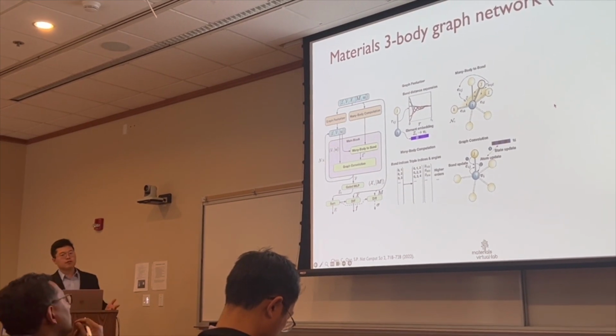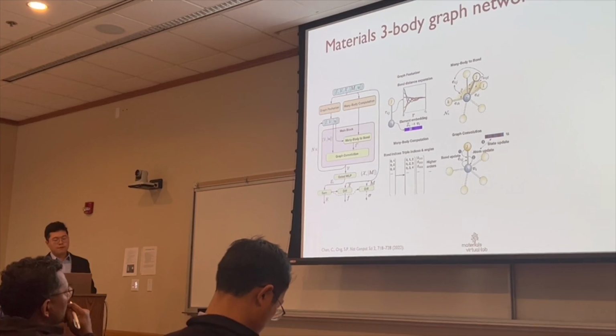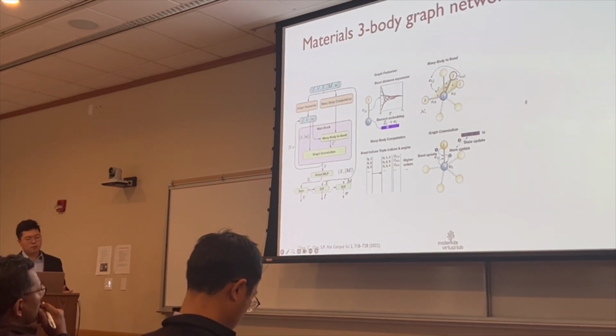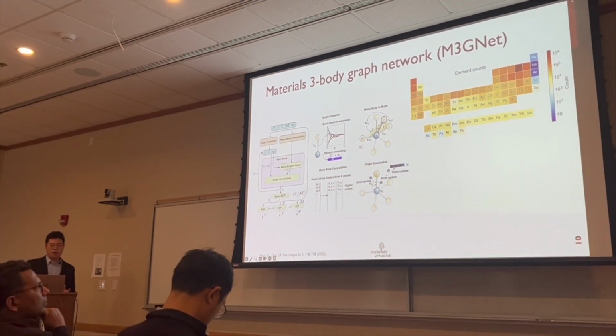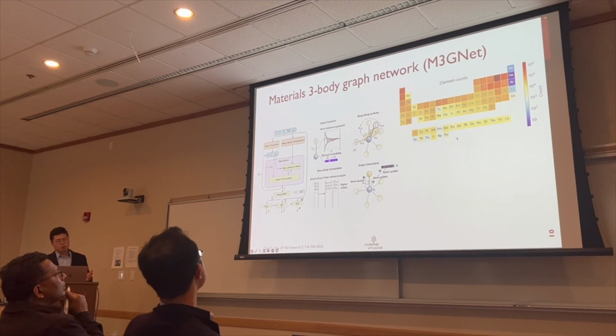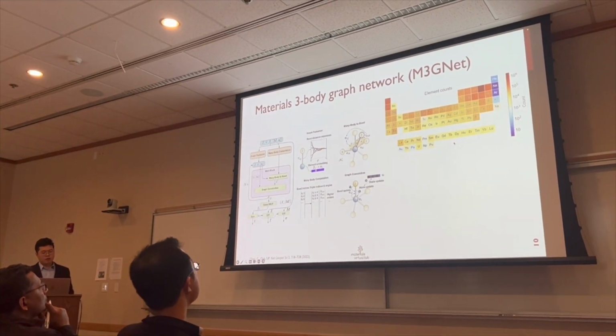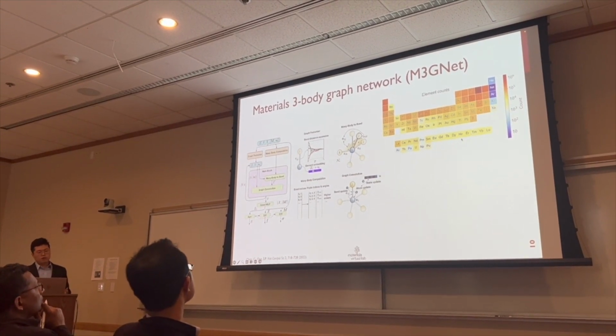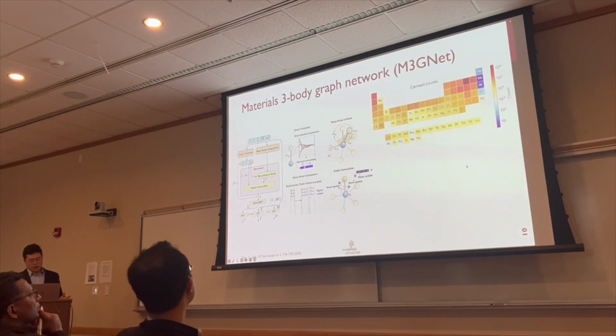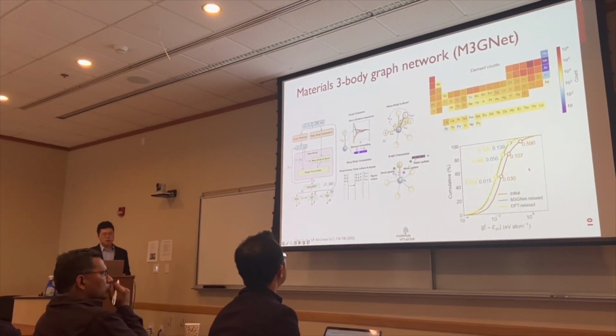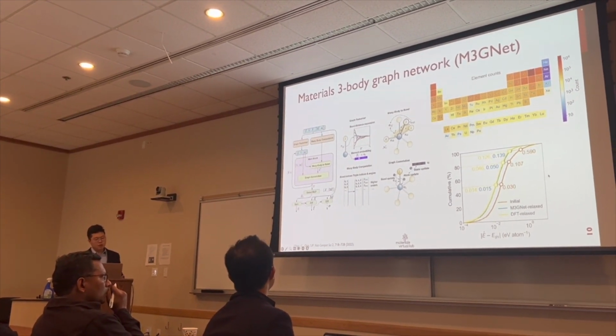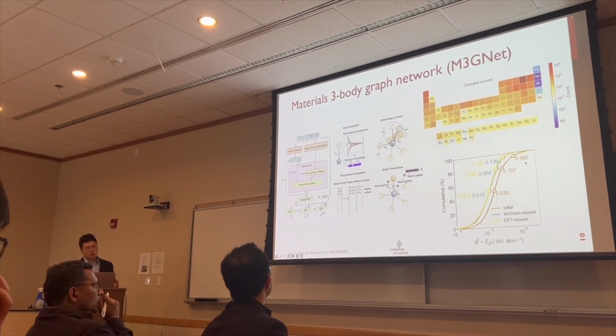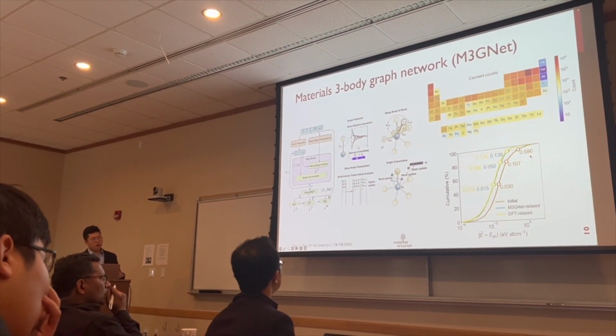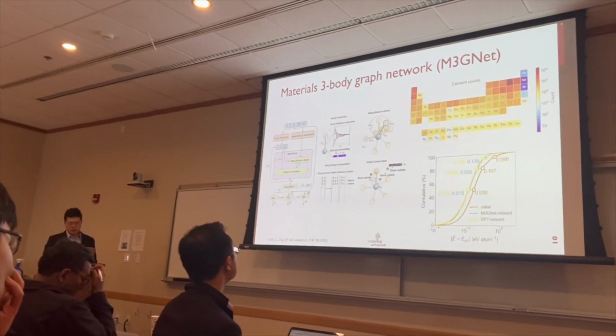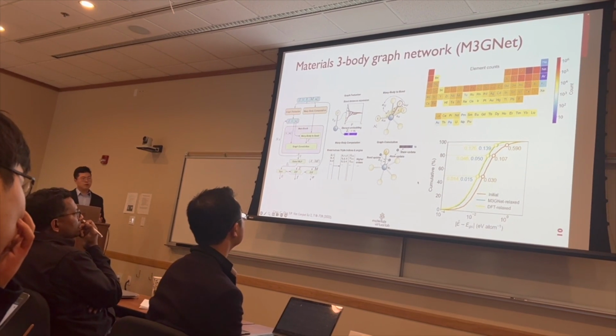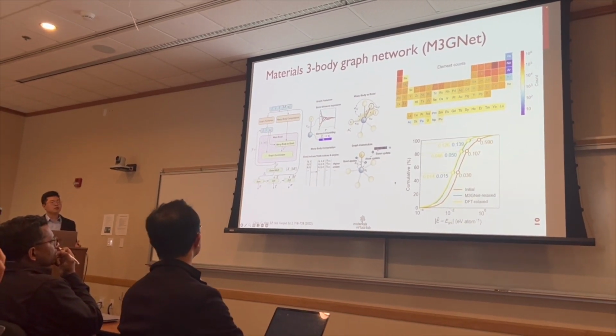Because of this deep learning framework, it enables the possibility of a universal machine learning interatomic potential model that can be trained on the whole periodic table. Indeed, this M3GNet is fitted with more than 100,000 training data points, which are DFT data from the Materials Project that span over 89 elements on the periodic table. This model is verified to have very good reliability for structure optimization. You can see that there is almost no difference from the DFT relaxation result for materials included in the Materials Project. So this model enables a lot of new possibilities, like large-scale screening of hypothetical materials and efficient sampling of structures.